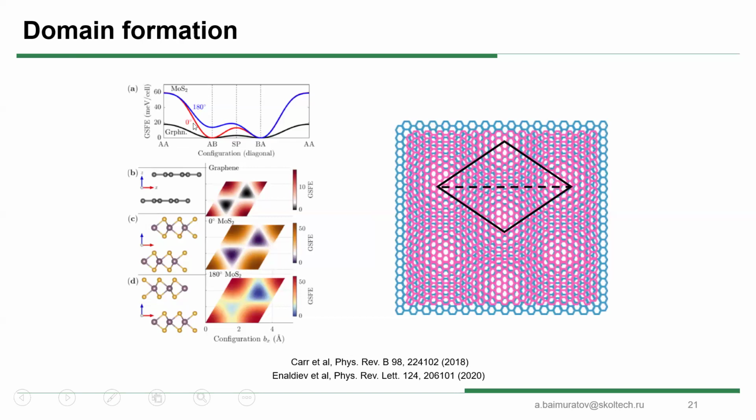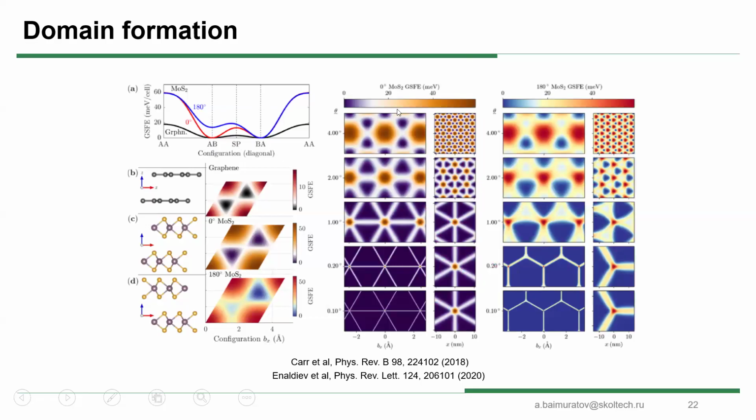And here we will have something called zero degree stacking or R stacking. And we have two optimal stackings. Let's call them AB or BA, with many different notations. And you see what happens when you start to optimize your lattice. You have two terms: strain energy and interlayer energy. You optimize this problem, and if you do everything correctly, you will observe that you have very large domains.